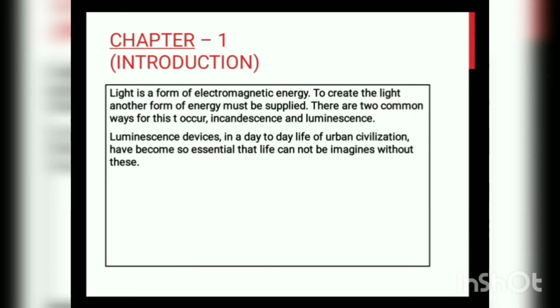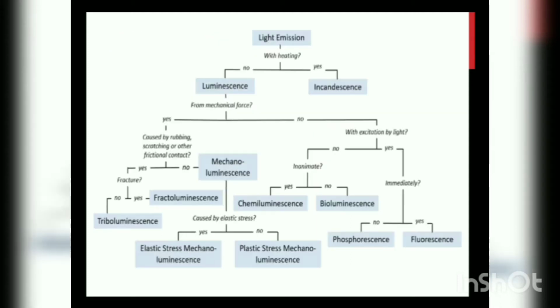In luminescence, when radiation is incident on a material, some of the energy is absorbed and re-emitted as light of longer wavelength. This is called Stokes' law. In this process, the wavelength of light emitted is characteristic of the luminescent substance and not of the incident radiation. The light emitted could be visible light, ultraviolet or infrared light.